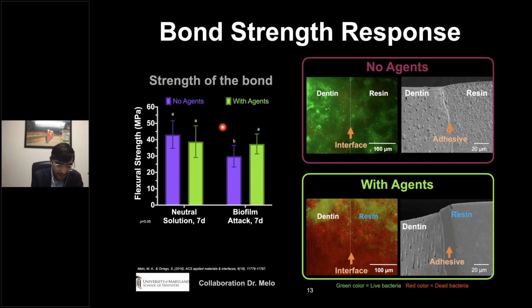As you can see here off the bat, if we keep the samples in the control solution with no biofilm attack, the bond strengths are comparable. They look pretty much the same, with no significant drop. But if we put the control sample with no agents and the sample with agents into the biofilm solution, we see a significant reduction on the bond strength of the group that had no agents. That showed us that the agents were providing some antibacterial activity, comparable to groups tested in the neutral solution.